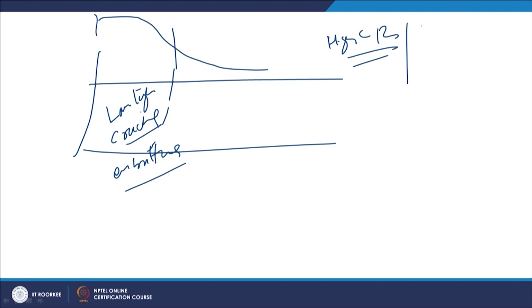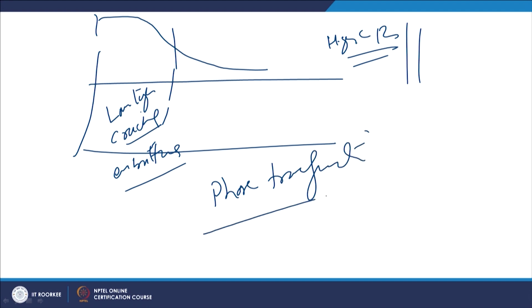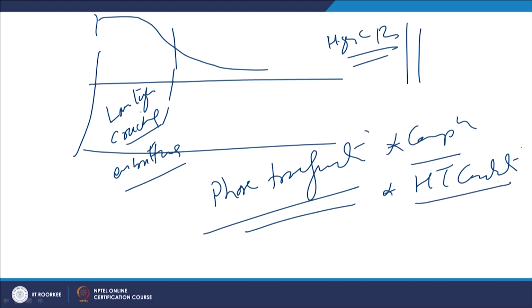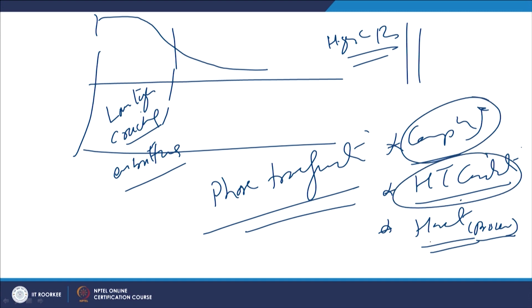But all steels are not sensitive to this kind of phase transformation. The type of phase transformation is, to a great extent, a function of the composition, the heat treatment condition of the base metal, and the kind of heat input given in the form of net heat input. Net heat input is a function of the welding process; heat treatment condition means whether it is in annealed, normalized, or quenched and tempered condition; or the composition, as there are steels categorized based on composition. A few are highly hardenable, and a few will offer higher hardenability as compared to others. So, about the composition, heat treatment and heat input related aspects, we will be talking subsequently as far as transformation hardening metals are concerned.